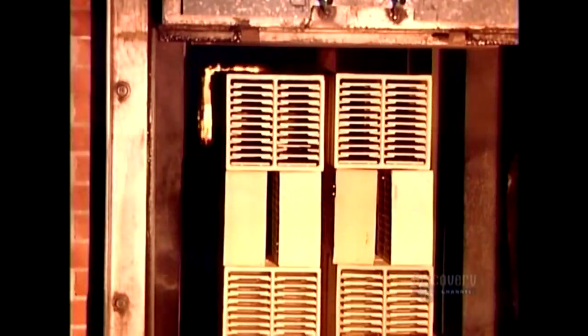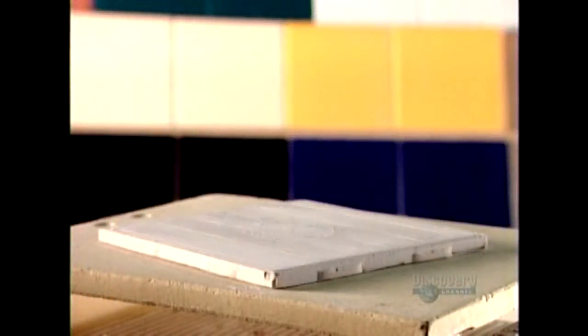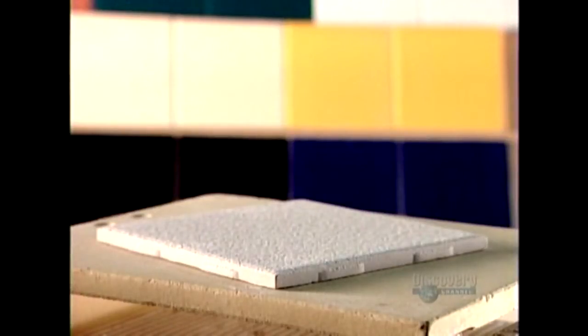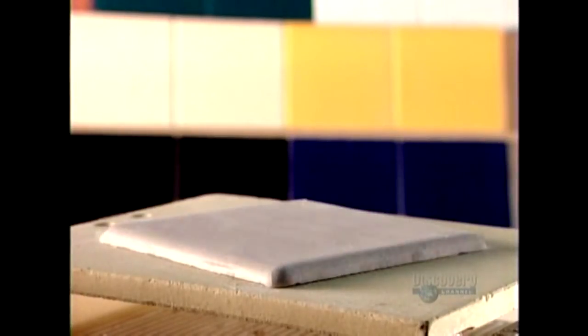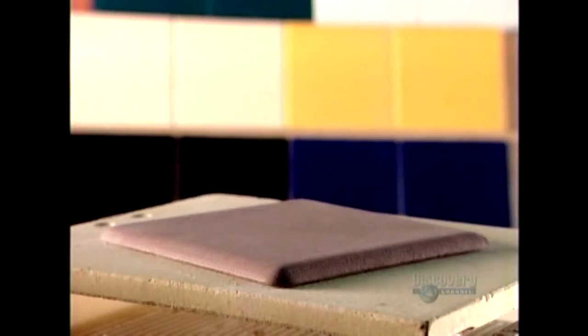Any sudden changes in temperature could produce thermal shock and crack the tiles, so it starts out at 200 degrees Celsius, climbing gradually to a peak of 1075 degrees, then descending slowly back to the starting temperature. After a cooling period that lasts roughly an hour, the tiles come out. They're now fully hardened and ready to have their back to the wall.